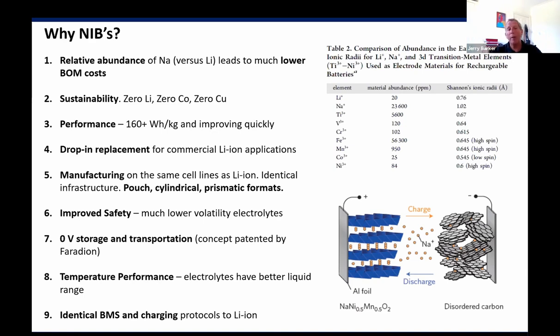So in terms of sodium ion, we're improving quickly, and we think we can get over 200 watt-hours per kilogram in terms of specific energy. And if we can do that, we start finding ourselves competitive in terms of energy density with good lithium ion, that's NMC and NCA. We're a drop-in replacement for commercial lithium ion applications. That's really important, right? You haven't got to re-engineer the application if you replace an existing lithium ion application with sodium ion. Another important aspect is the manufacturing we do is exactly the same as lithium ion.